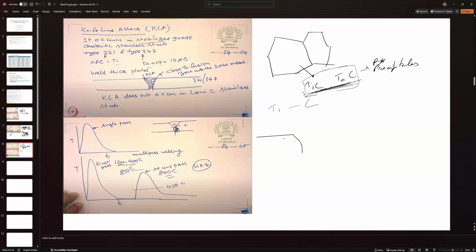This is your sample you're trying to weld, like sheets. During the first pass, you weld this much area, suppose. What will happen close to this fusion zone? The area close to this zone reaches a temperature above 1200 degrees Celsius. This causes decomposition of these carbides, and once it cools down, some precipitation would form, but here you've lost most of the carbides.